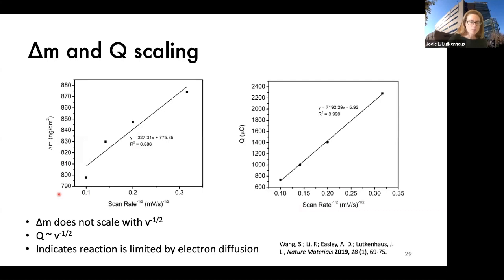And we do that for each scan rate. So on the left is delta M versus scan rate to the -1/2, and on the right is Q versus scan rate to the -1/2. Q is linear with negative square root of scan rate. That indicates to us that the reaction is diffusion limited by the electron, not necessarily diffusion limited by the ions. And this finding was not surprising, considering that PTMA is not really known for its electronic conductivity.